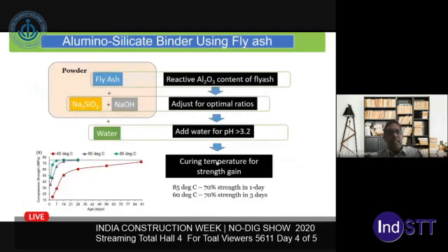So now, what we did, understanding the chemistry of the fly ash, is we developed a process using this low reactive fly ash, which is predominantly available in India. By determining the reactive oxide contents and optimizing how much activators need to go in there, where activators are primarily provided in the form of sodium silicate and sodium hydroxide, and understanding their role in the entire reaction chemistry, we've been able to produce geopolymers which consistently give us strengths of about 80 megapascal. We've also reduced the temperature demand for curing down to 40 degrees Celsius, which is a temperature common in summers in India. For 6 months of the year, the high temperature in most of India exceeds 40 degrees. So we're able to achieve a binder that gives us 80 megapascal strength using fly ash, which is a waste material. And this entire process has been developed by understanding the chemistry of the process.